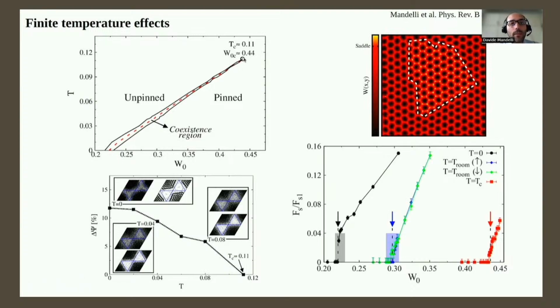The coexistence line ends at a critical point, and we actually have some evidence that this is a critical point where the transition becomes second order, by studying the hysteresis in the static friction measured ramping up and ramping down the substrate potential. The hysteresis that is present below the critical point completely vanishes at the critical point. We also studied some susceptibilities and observed signatures of divergence of susceptibility. So we have other hints that this is indeed a critical point for the Aubry transition in finite temperature incommensurate monolayers.